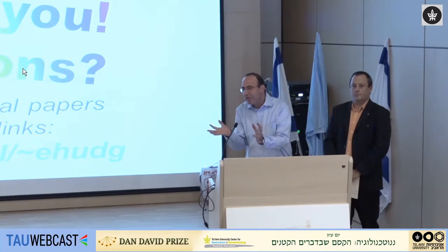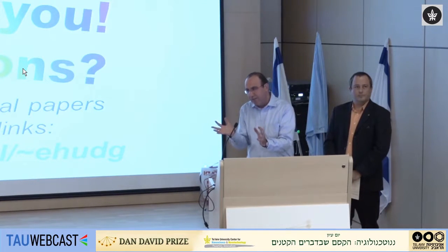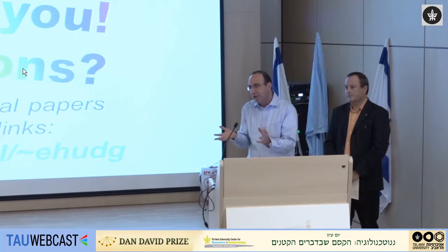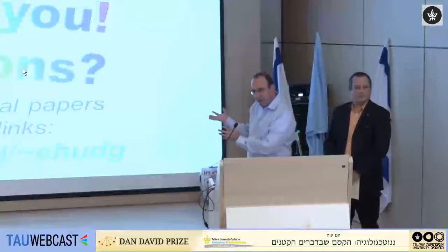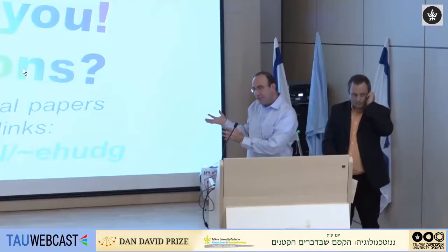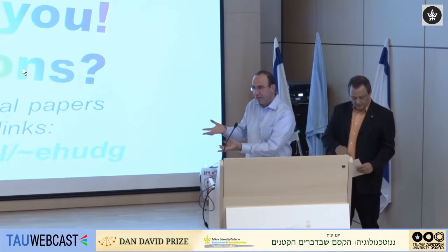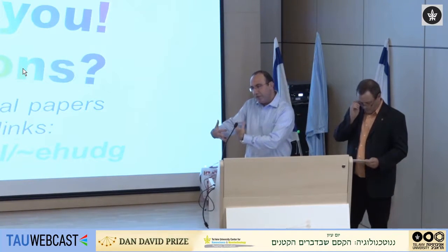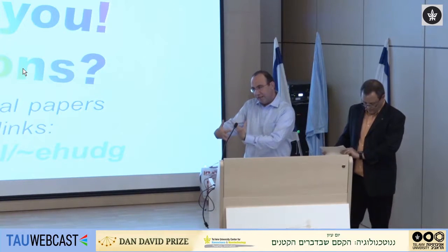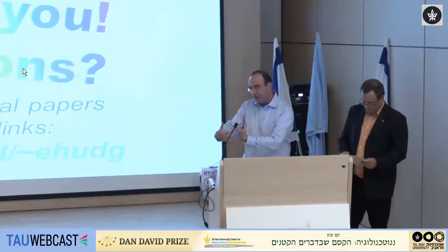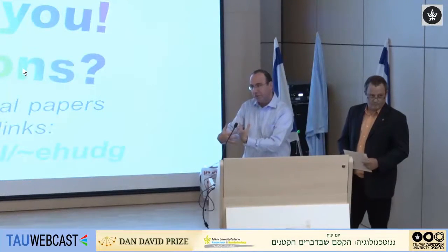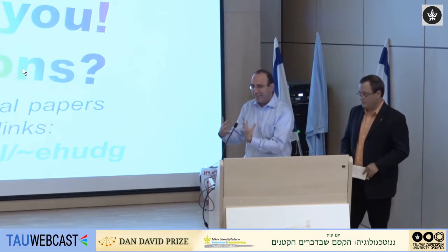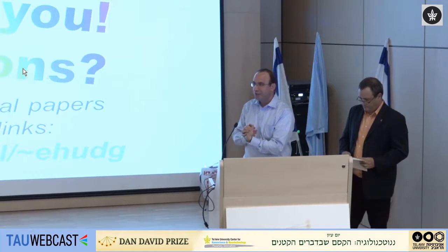So the role of guanine: it's done only with guanine, and as you know, guanine is used in nature not only in those examples that I mentioned, but also at the molecular level, like G4 quadruplex and others. This is due to the pattern of hydrogen bonding and the planarity of the molecules that allow the formation of the structure. Why are these uniform structures?